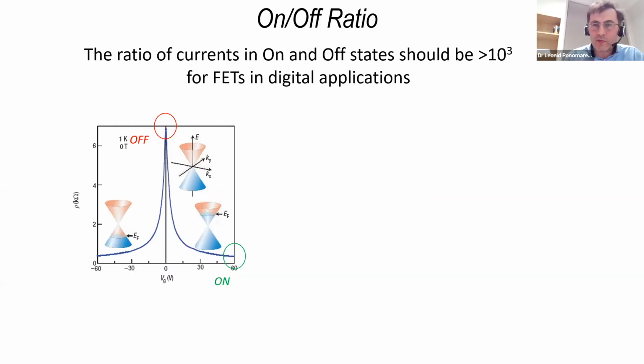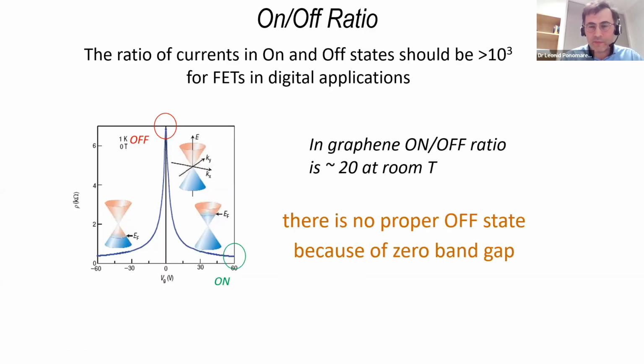So all of those who gave answer 10 were correct. And unfortunately, all of those who think that graphene is already suitable as a field effect device for digital applications were wrong. In the best graphene devices, the on-off ratio at room temperature is only 20. So there is no proper off state in such a device, and the reason for that is that graphene doesn't have a band gap. So the conduction band and valence band just touch each other. And if there is no band gap, well, the material cannot be insulating.